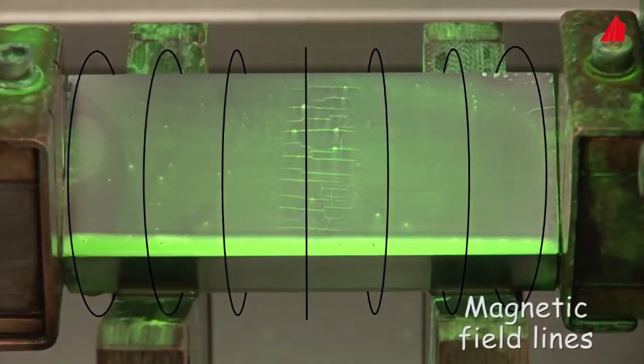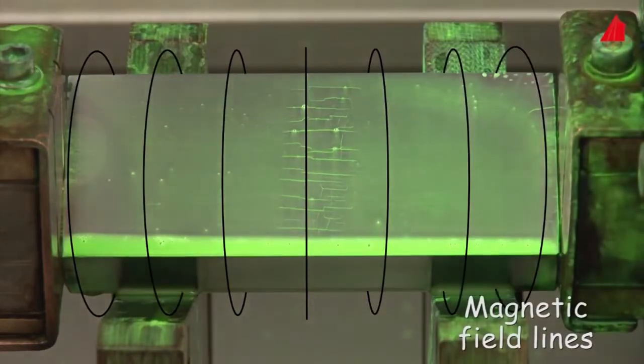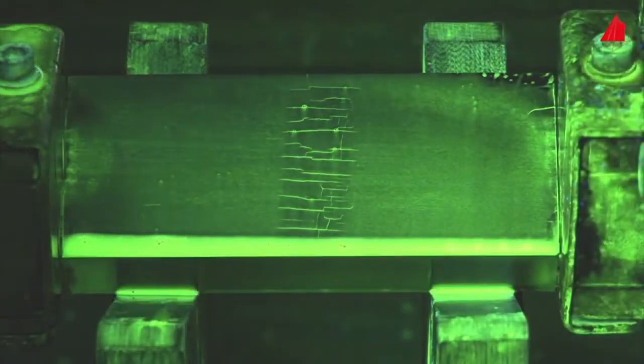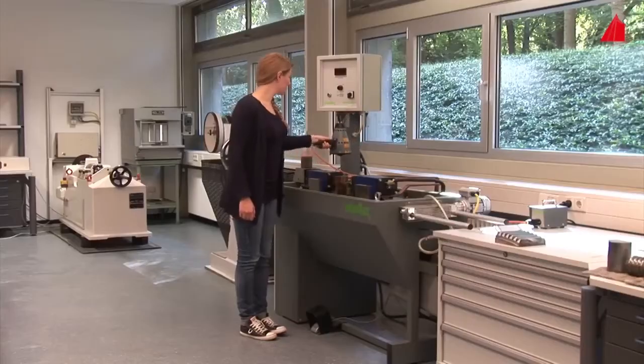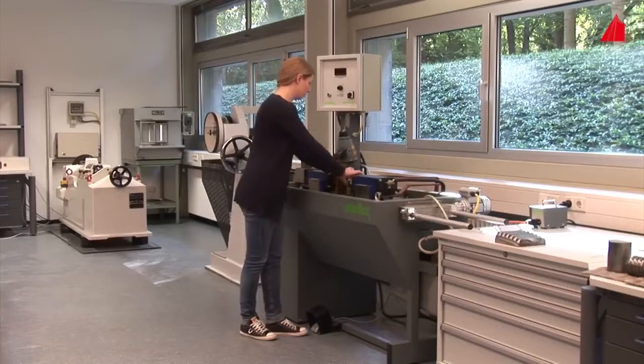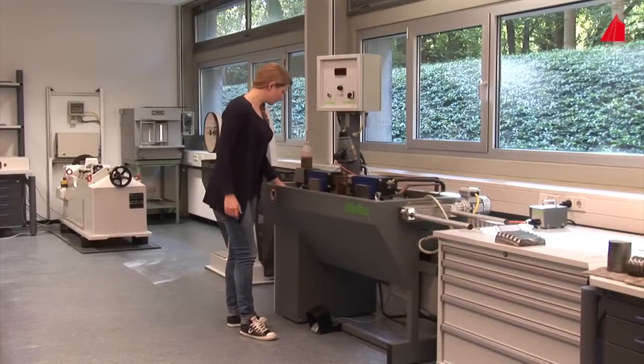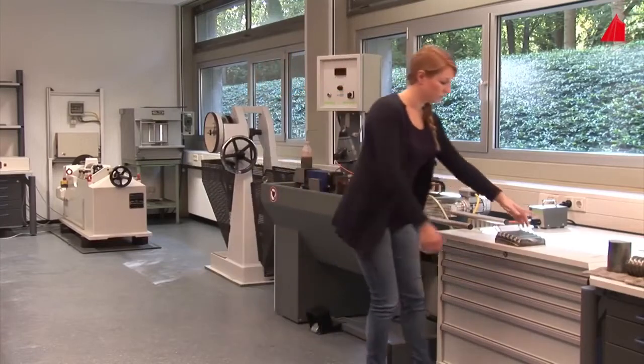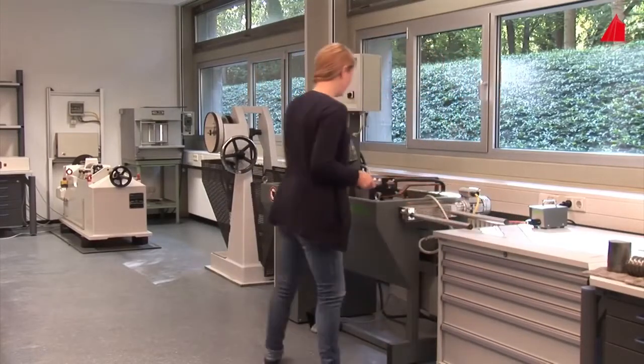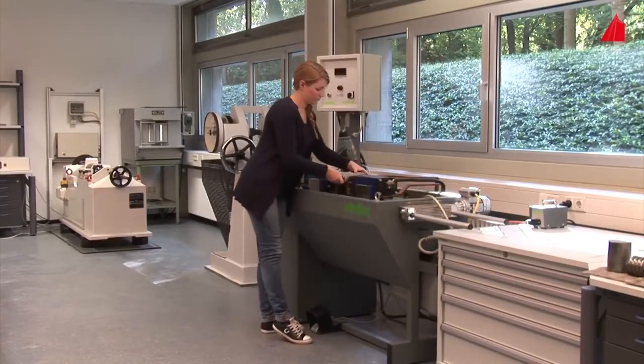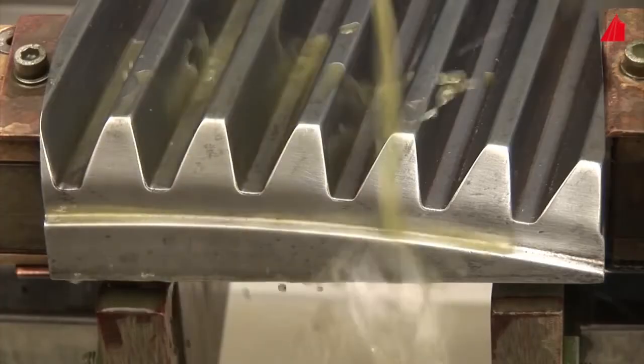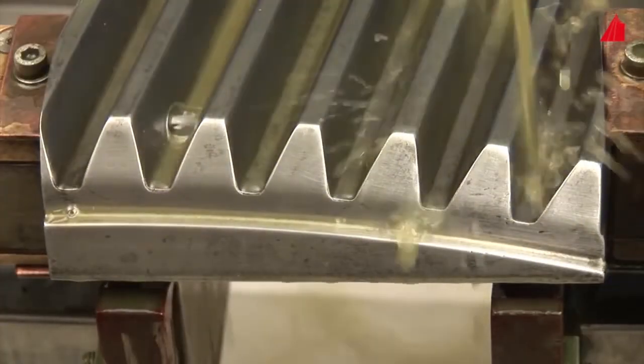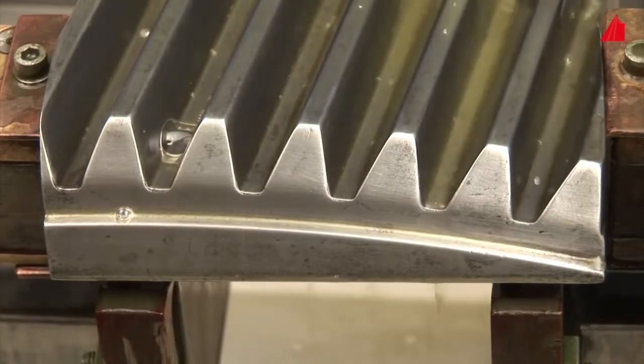The tested sample is a hardened sliding guide. The cracks have been formed during the hardening process and the subsequent grinding operation. Still another test piece has to face the magnetic particle inspection, a section of a large gear wheel. The same procedure again. Placing the gear wheel between the magnetic pole pieces, magnetizing and applying magnetic particle suspension.